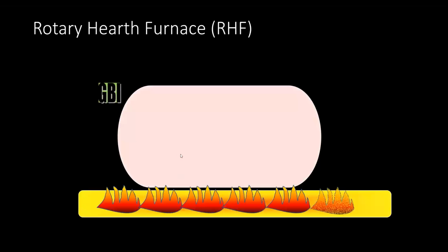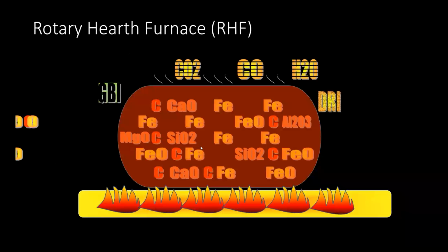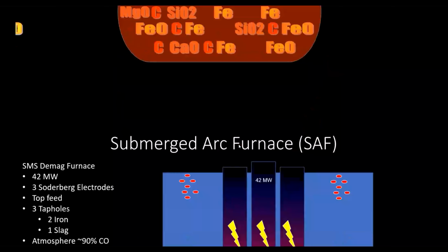So looking at the green briquette and the rotary hearth furnace, it's not showing my animations very well, sorry. But the goal was to show that you have FeO, Fe2O3, Fe3O4 in here. The CO drives off the oxygen, and hopefully you end up with primarily iron.